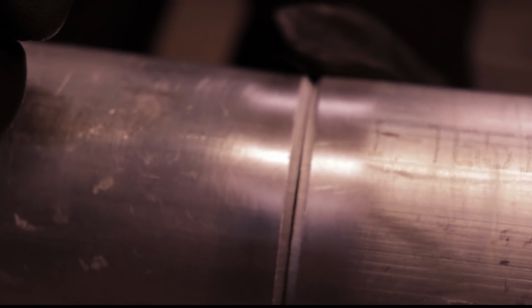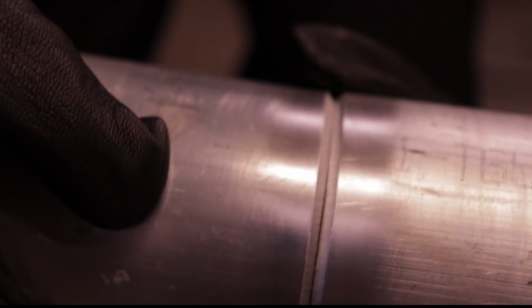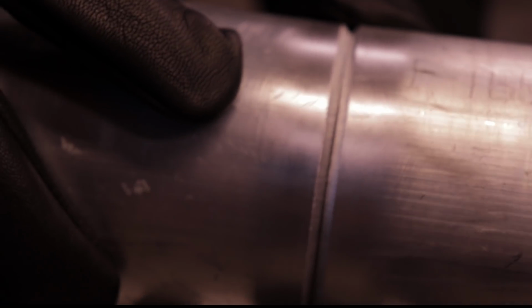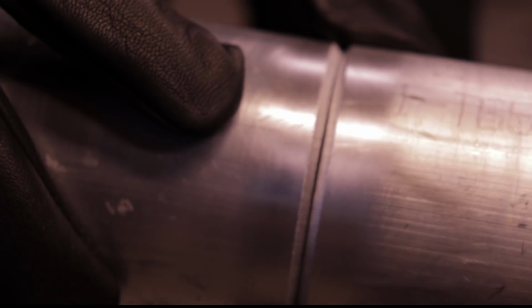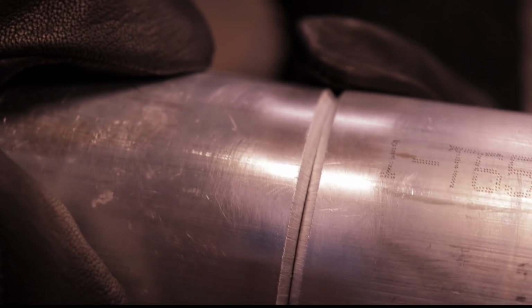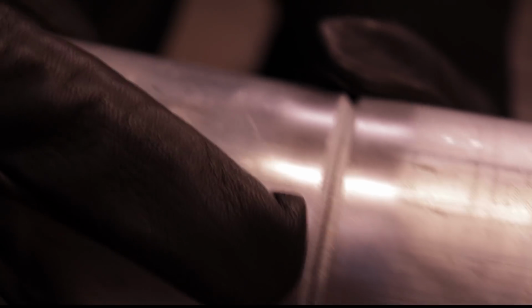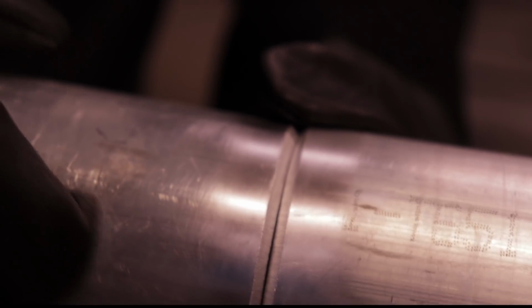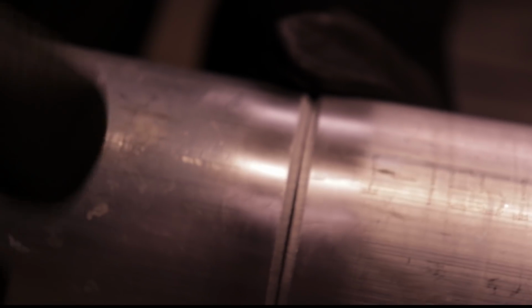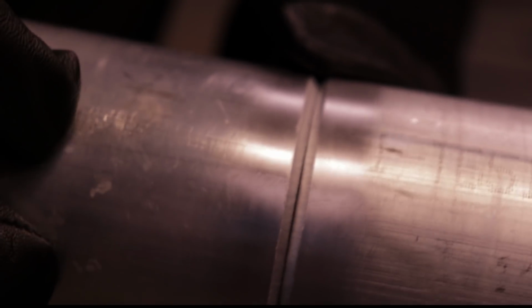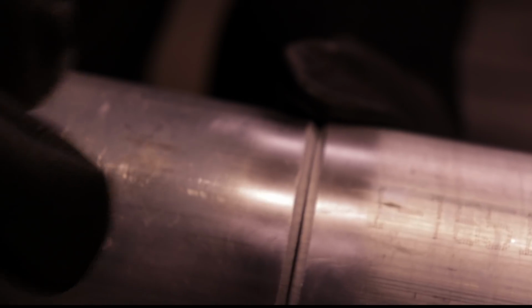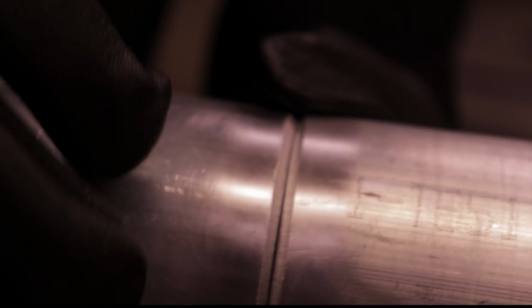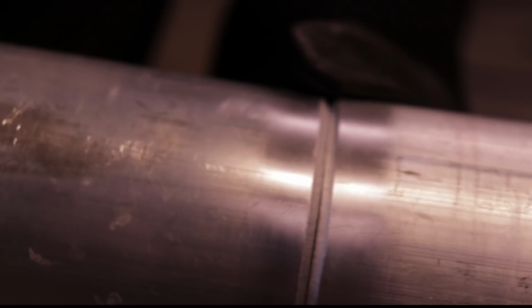3-inch Schedule 40, if you 45-degree bevel it like this, it's a pain in the butt. You gotta really heat it up for your root pass, then you gotta do a cover pass on it after that. 2-inch Schedule 40 is the most that I do in one pass with a 45-degree bevel. Anything over that, like 3-inch, I like a J groove. The problem is we don't have a router that can put a J groove in it, so I have to 45 it and then come in there and cut it with basically a flap disc to get my bevel the way I like it.